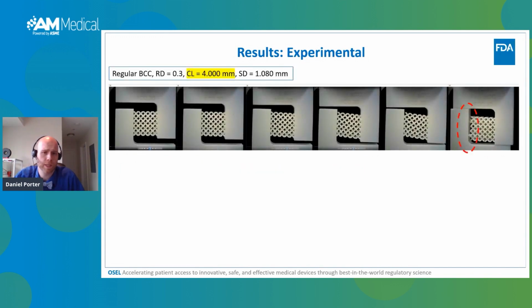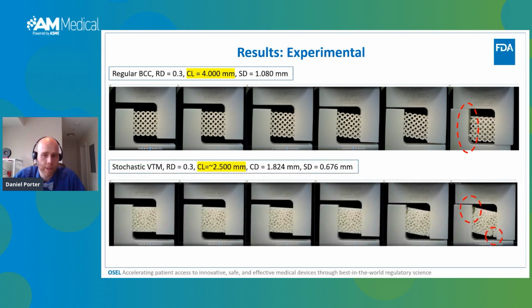Here are some shear samples that we loaded. These are kind of interesting. You can note that one of the failure modes is almost a perfect vertical separation from the grip wall. This is not the only failure modality that we see, but it is one that we notice quite a bit. The Voronoi shear sample, as it's being loaded, has a different failure modality shown here. You get tearing at the struts at the top left, and then a little bit at the bottom right area, which shows that the weak points on these lattices vary.